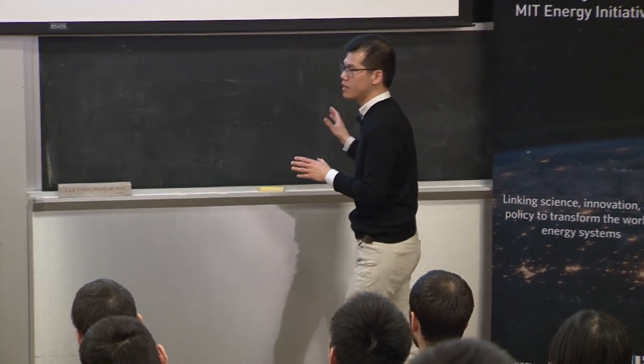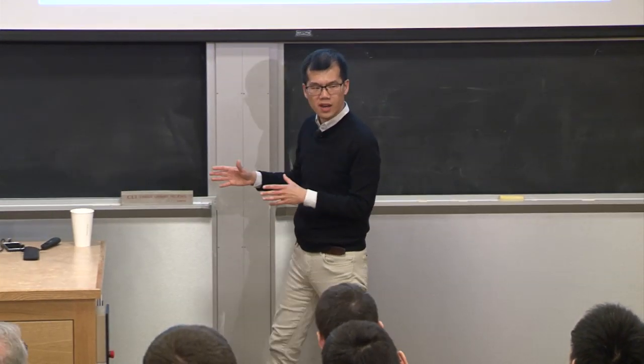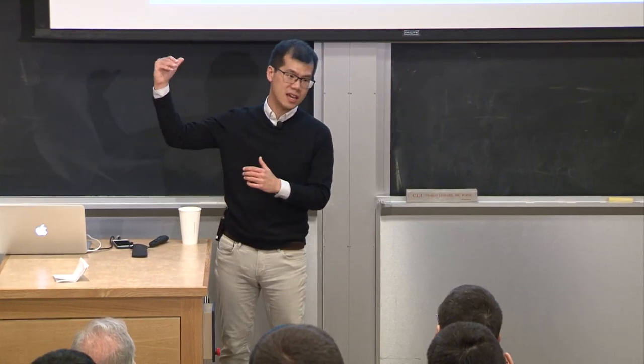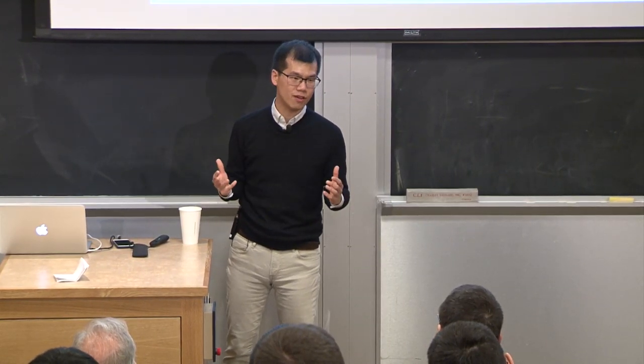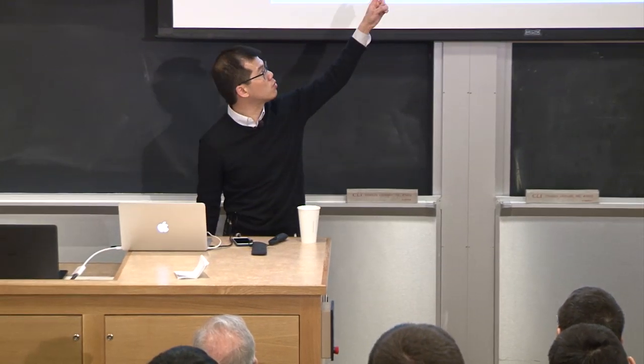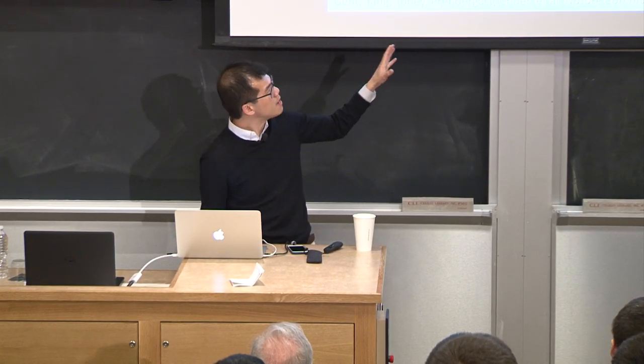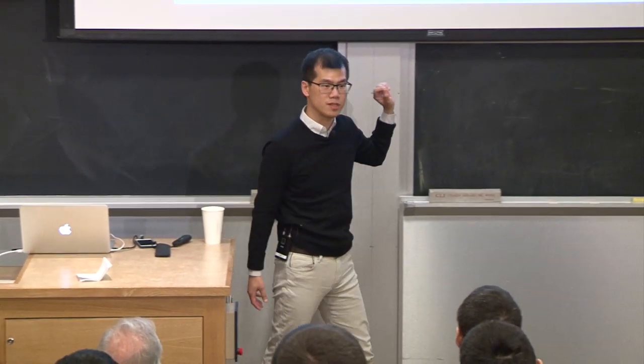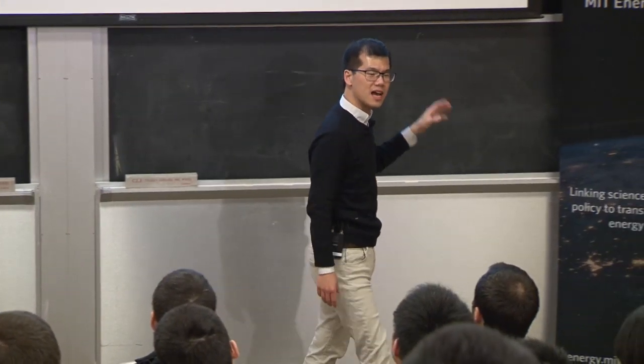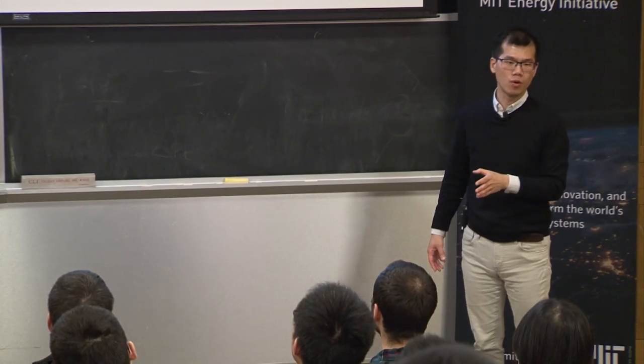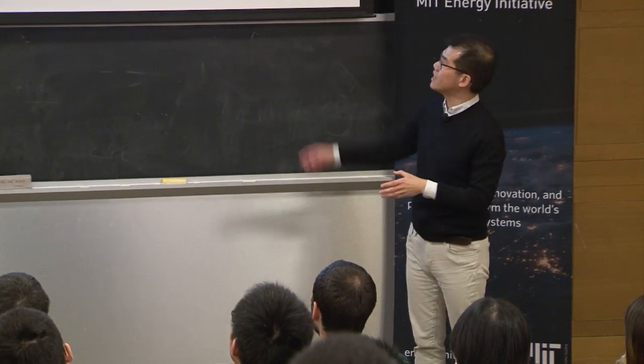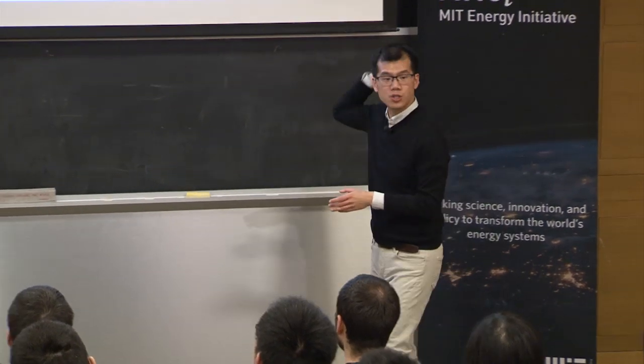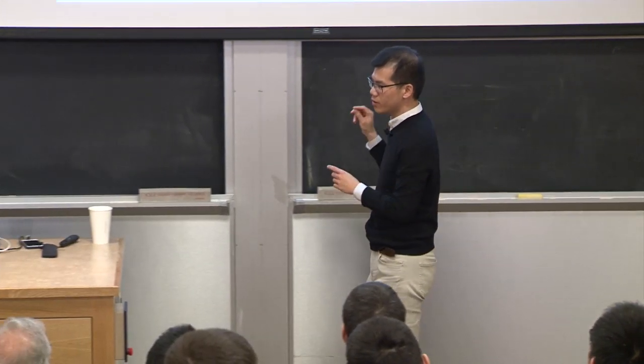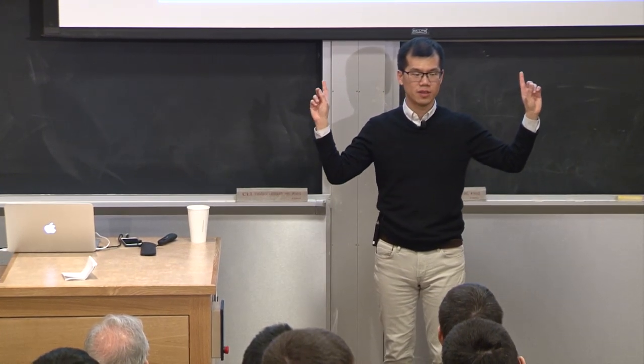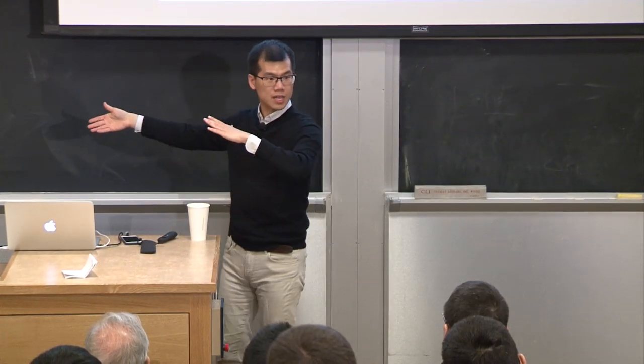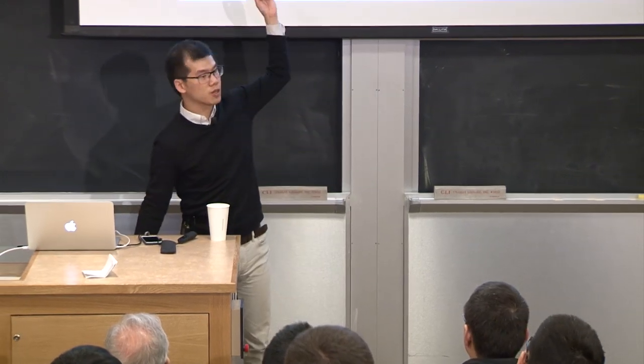So the simple chemistry explanation is that all of these things happen because you're putting the transition metal in a very oxidized state, and it's trying to stabilize itself. And the way it stabilizes is by creating these dangling oxygen. So there may actually be very few ways to escape from this pathway. So what this is telling us is that structural rearrangement must come with the additional oxidation, because that's the only way the oxygen can stabilize. It's either this or the oxygen leaves. But what is very interesting about this material is the metal can go back. So as we reduce the material, as we discharge it, the metal actually goes back to the left situation.